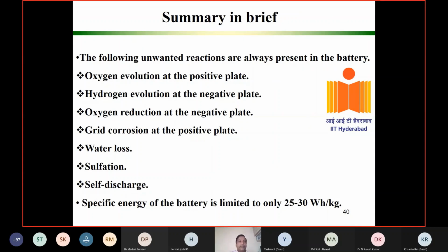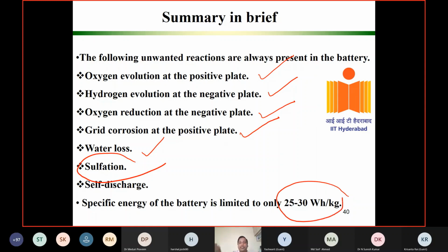So again, in summary, oxygen evolution always takes place at the positive electrode, and oxygen reduction at the negative electrode in the valve-regulated cell. Hydrogen evolution at the negative plate, oxygen reduction at the negative plate, grid corrosion at the positive plate. Water loss is because of hydrogen evolution and grid corrosion together. Sulfation always happens in both electrodes, but more at the negative electrode, and the self discharge is again because of lead sulfate. And specific energy is very, very low. These are the areas you can always work on. I'll come to this area in later slides. Any questions at this point, my friends?